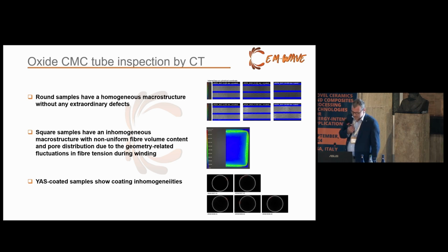Anyhow, it's very nice to see on the CT images what errors we can make. You see in the rectangular core that, due to the rectangular core, we have different tension strengths on the sides. You have maximum pressure on the fibers, and in these areas your matrix is squeezed out, and in the plane you have almost no forces, and in these regions you have an enlargement of polymer matrix. So it was not so nice to take the rectangular core, and that's why we used the round tube in the rest of the assembly project.